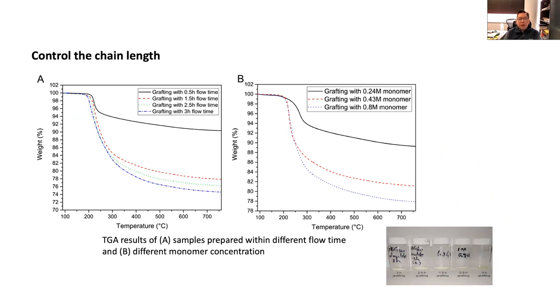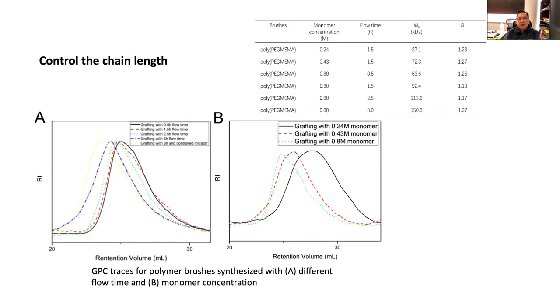initiator followed by polymerization. And in looking at the reaction rate or flow time, and also the ratio between the initiator and the monomer, clearly we can see that the slower or longer flow rate time or residence time produce higher molecular weights or more grafted polymers, as well as the introduction of a higher concentration of monomer. And then finally, by controlling the chain length, we can observe this also by GPC. So the traces here actually give us the corresponding molecular weight. The polydispersity is around 1.2, increasing with concentration or residence time or flow rate.